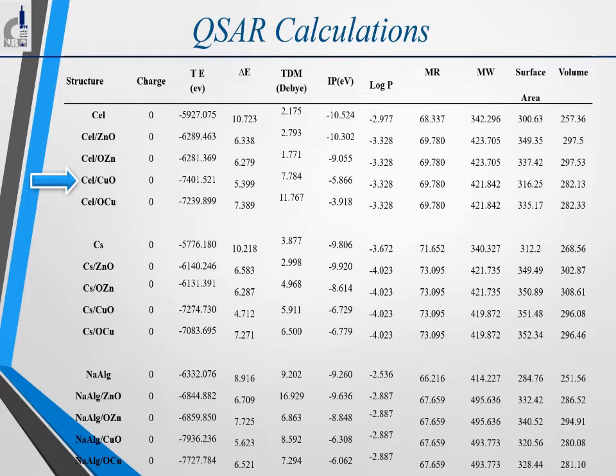Also for the chitosan group, chitosan copper oxide follows the same behavior, which indicates that chitosan copper oxide is the most possible and enhanced structure for this group. Finally, for the sodium alginate group, there is no significant change in the electronic properties when the sodium alginate interacts with metal oxide.